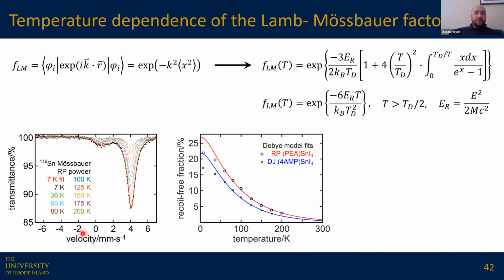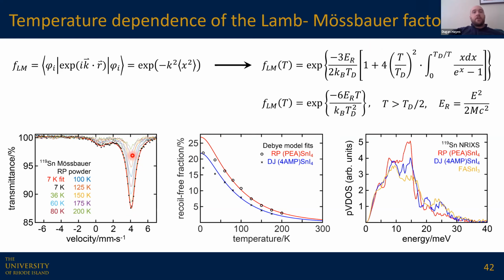And so here's some data that we have for these tin halide perovskites at temperatures from 7 Kelvin up to 200 Kelvin. You can see the spectrum gets attenuated, and we can fit this to the Debye model, get a Debye temperature, and figure out the recoil-free fraction or the Lamb-Mossbauer factor that way. But importantly, what I want to stress here is that the magnitude of the absorption changes, but the spectral shape does not change at all.